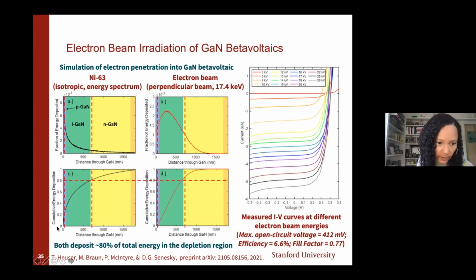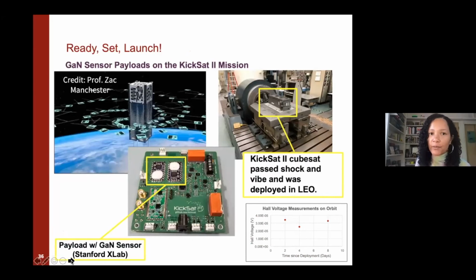And so what he's showing here is cumulative energy deposition for nickel-63 versus an electron beam in a common scanning electron microscope. And so they both deposit 80% of the total energy in the depletion region, which would allow us to generate current. And so we have an open circuit voltage of 412 millivolts. So it is working as a harvester. And our devices were deployed in LEO.